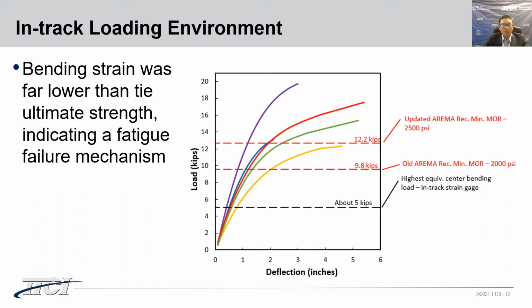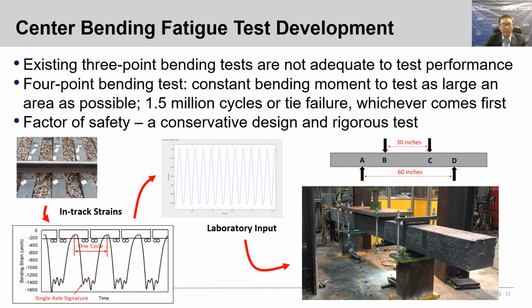As the plot shows here, the black dashed line represents the measured in-track strain values from FAST and revenue service testing. As we can see, the in-track bending loads of composite ties were well below the tie's ultimate bending strength, MOR. Therefore, material fatigue is believed to be the failure mechanism for the observed cracking. This slide shows how we developed the center bending fatigue test to address the center cracking issue, from in-track measurement to the final test setup.